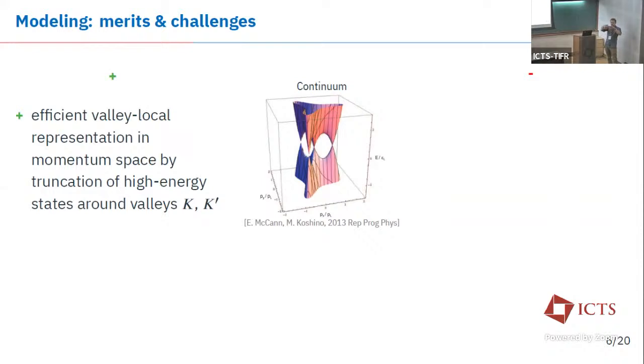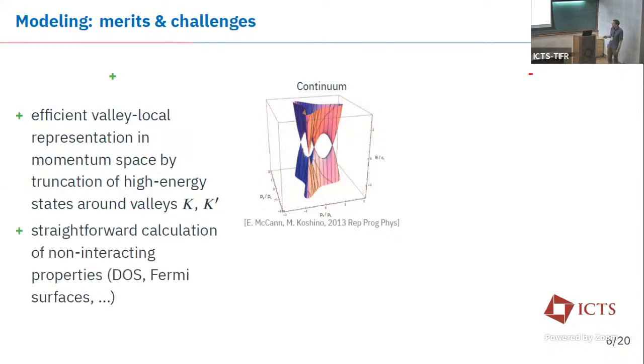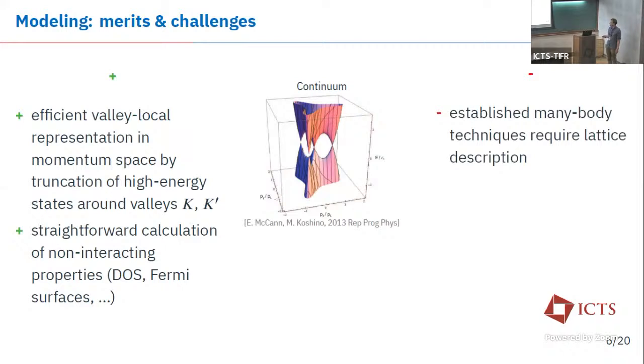So you only care about those portions of the Brillouin zone where all your low energy electronic states lie. And in Bernal bilayer graphene, those lie around the valleys K and K prime. You only model a tiny region around those valleys and you have all the low energy excitations. And of course, non-interacting properties are very straightforward to calculate using this approach, and actually even more efficient than in a tight binding model, because you only need very few degrees of freedom to write down this k.p model.